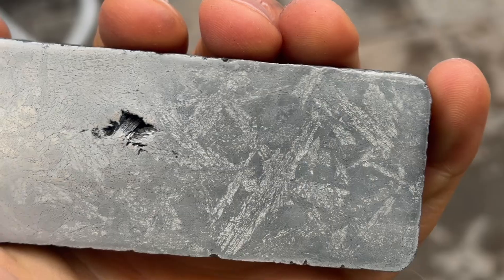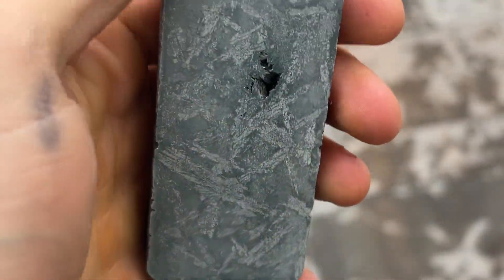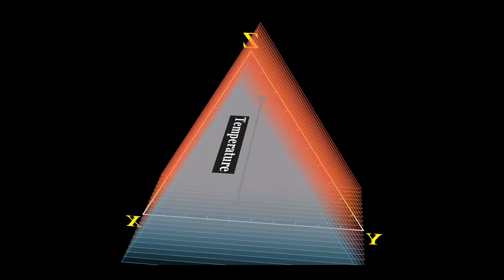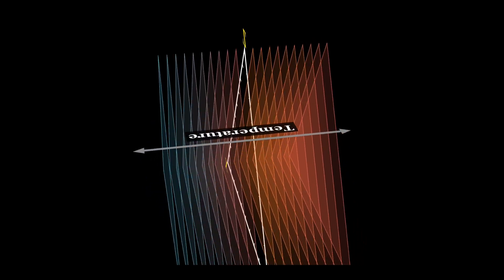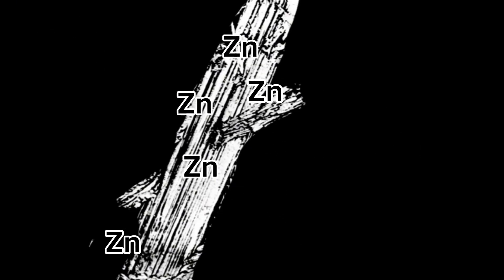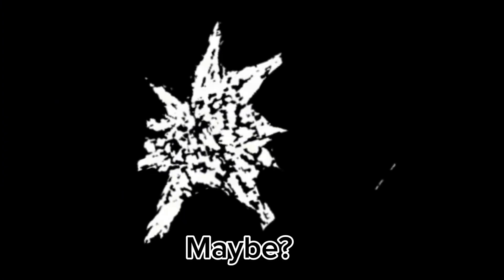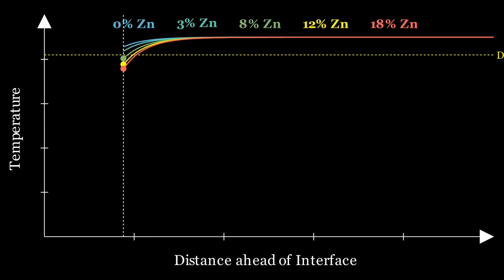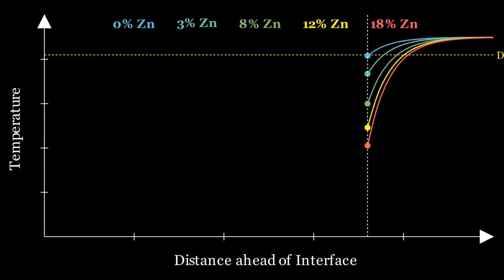It's worth stating that constitutional undercooling is not the only factor at play. The equilibrium crystal shape of the intermetallic could also change just from the presence of zinc in the liquid. For example, aluminum potassium sulfate crystals grown in different solution chemistries take completely different shapes, because the solution changes which crystallographic planes have the lowest energy. The same thing could be happening as our metal crystals grow in zinc-doped liquid, though this is more difficult to differentiate. I think the degree of undercooling between each sample is the primary driver of the change in microstructure, but changes in surface energy or zinc incorporation into the intermetallic could also be playing a role.